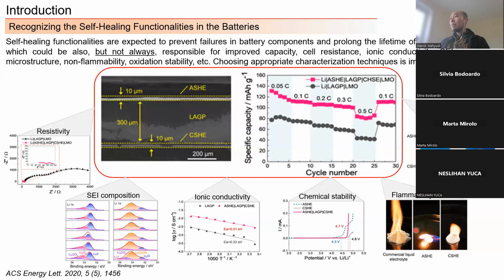We can say that some self-healing materials not only perform the self-healing functionalities, such as recovering the initial structure of the materials after cracking, or after a scratch or cut, but also they may give some additional benefits, like a low cell resistance or SEI composition, or improve the other properties of the materials, as shown by this reference published in 2020, the authors applied